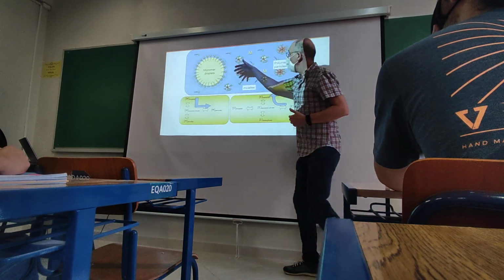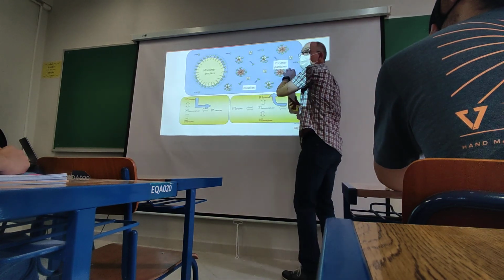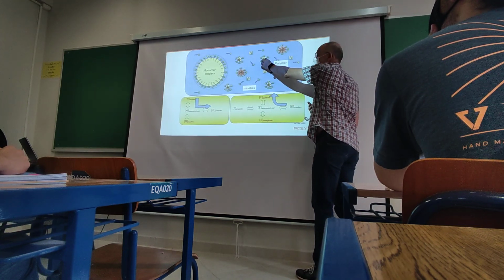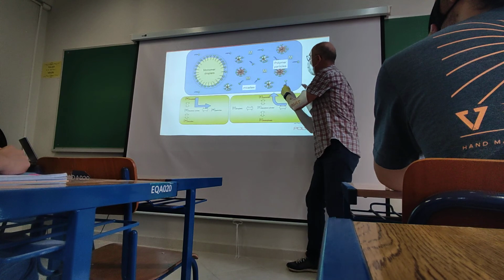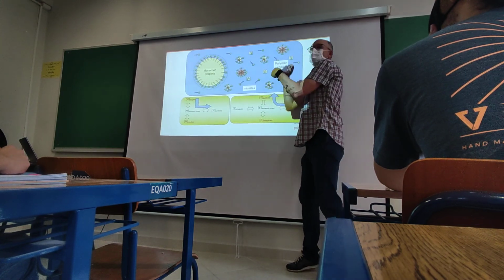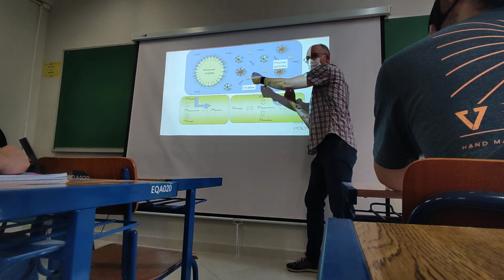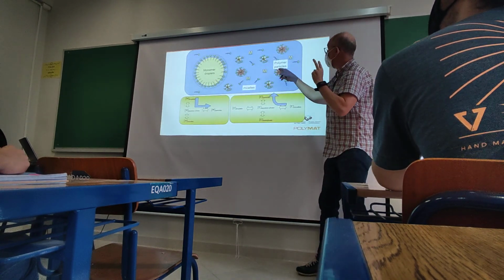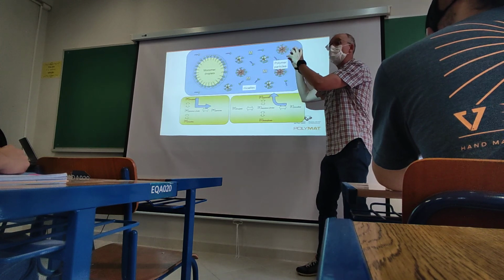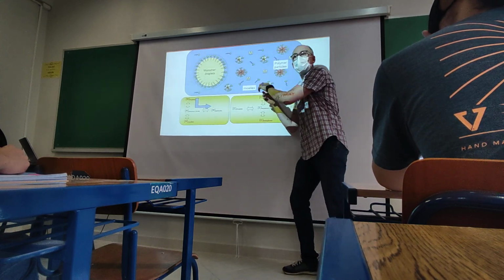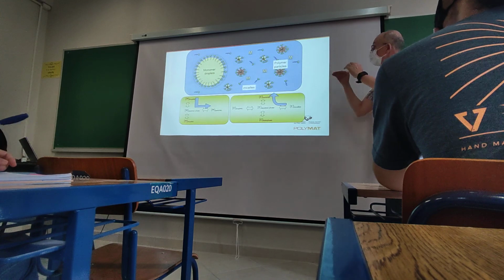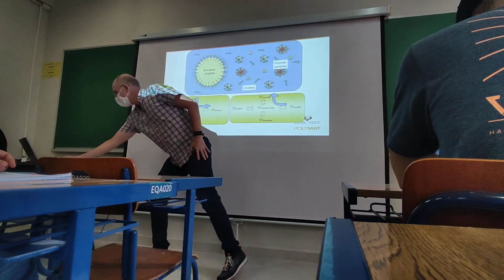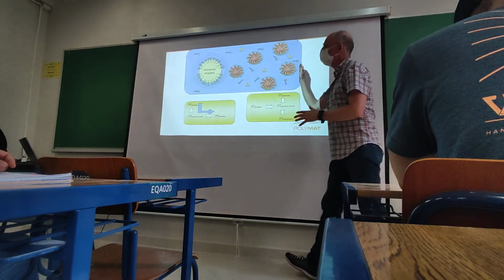So we will continue doing this, polymerization occurring here. Micelles will be destroyed also, because surfactant will go from the micelles to the particles, or because the micelles are becoming polymer particles because of entry of radicals. So micelles will continue disappearing because of two facts: we need surfactant to stabilize the growing particles, and radicals will enter and they will become polymer particles. So this process continues until we run out of micelles, and we will end up in this situation.